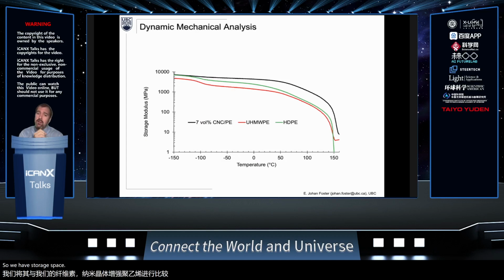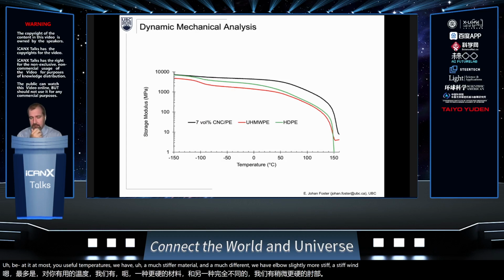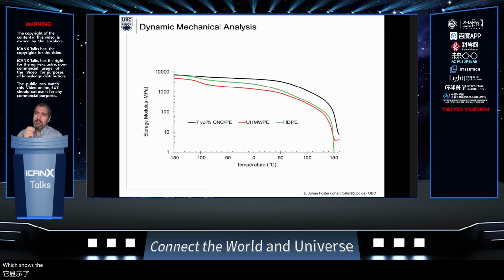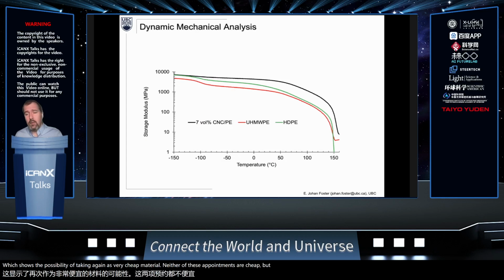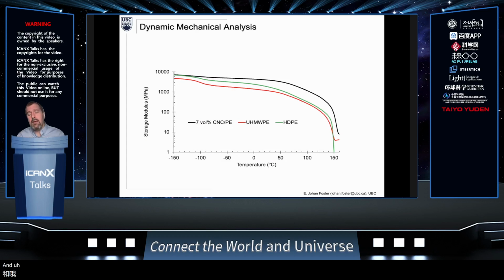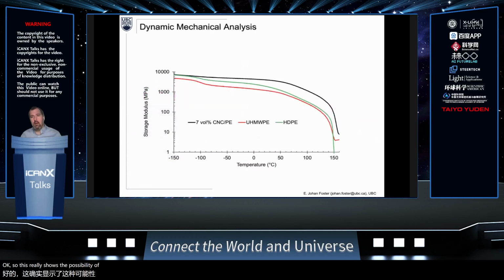So we have storage modulus as a function of temperature. So this is dynamic mechanical analysis. And we can show that at most usable temperatures, we have a much stiffer material. Not much stiffer. We have slightly more stiff material, which shows the possibility of taking, again, a very cheap material. Neither of these polyethylenes are cheap, but other ones are, and create a reinforced composite that allows you to use cheap materials to make higher end product. Okay, so this really shows the possibility of scale.